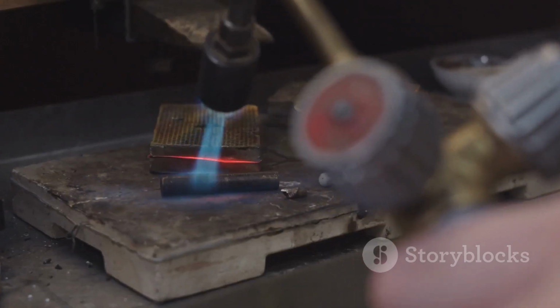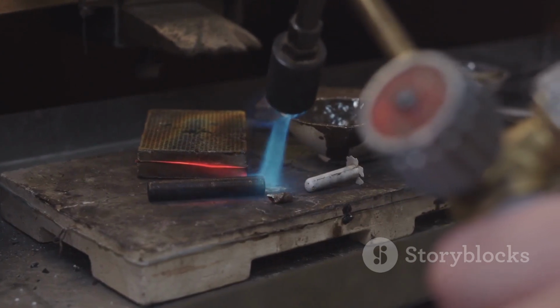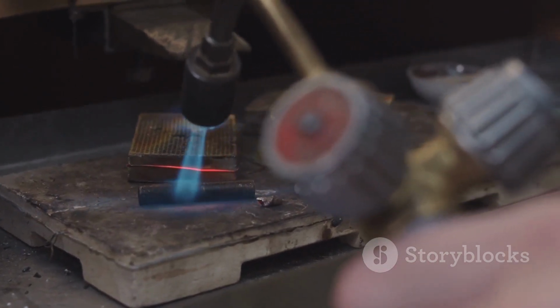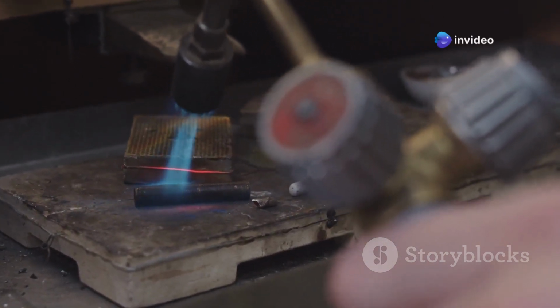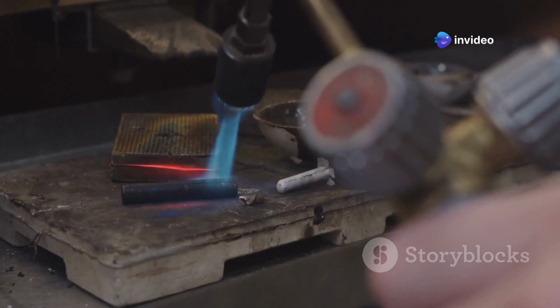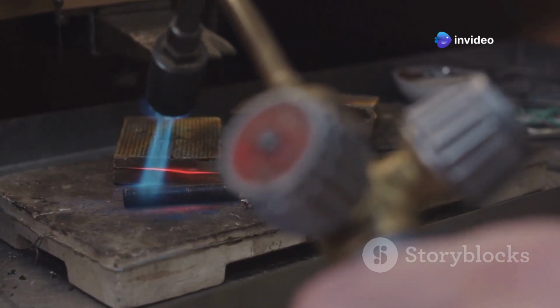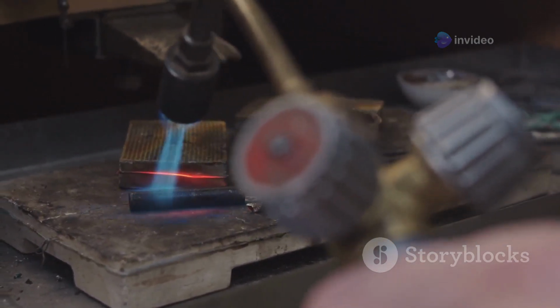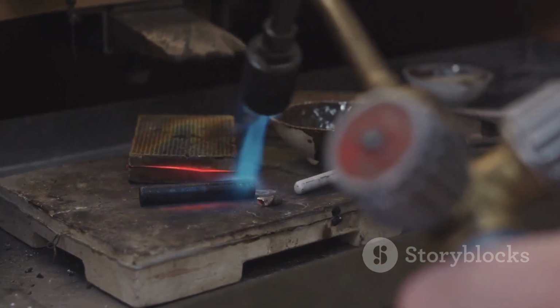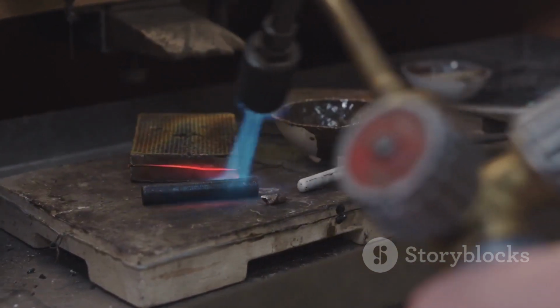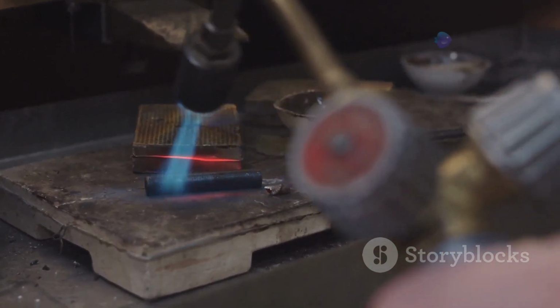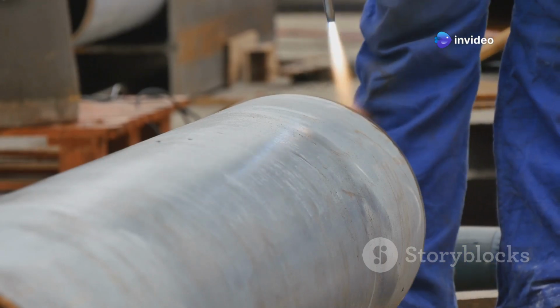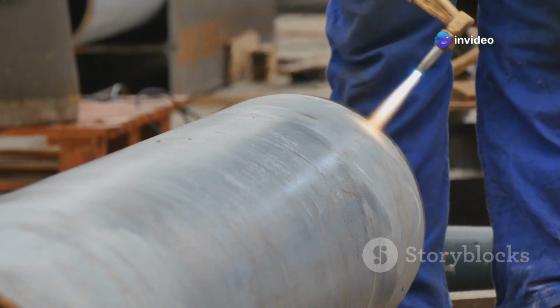This oxide layer has a much higher melting point than the aluminum itself. While aluminum melts at around 660 degrees Celsius, the oxide layer melts at over 2000 degrees Celsius. This means that if the oxide layer is not removed before welding, it will not melt and will create a barrier that prevents proper fusion of the metal. If you don't remove it before welding, you'll end up with a weak, contaminated weld.